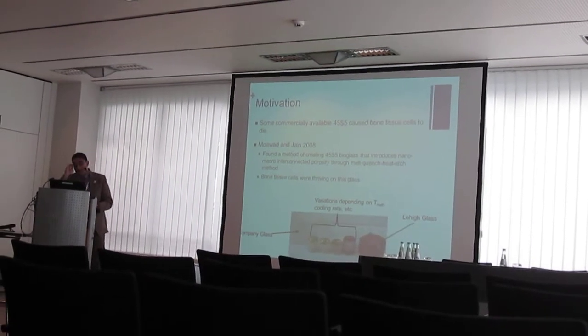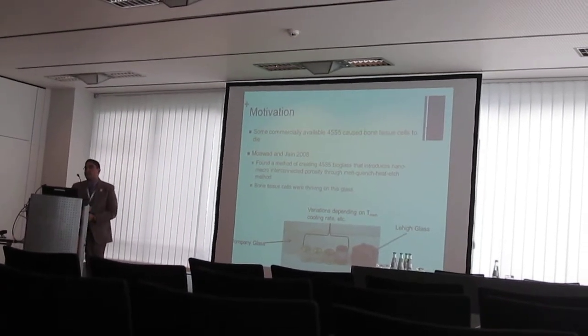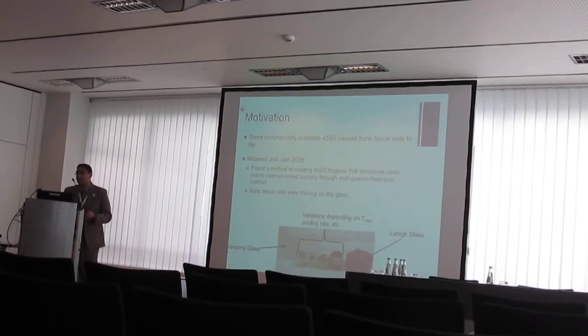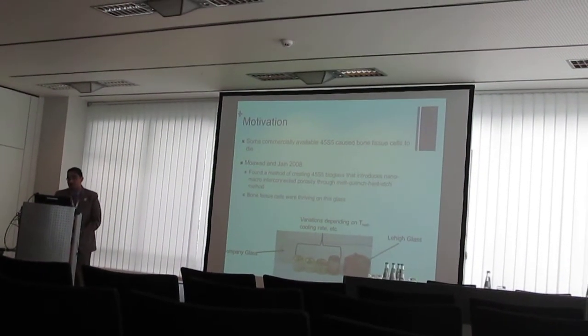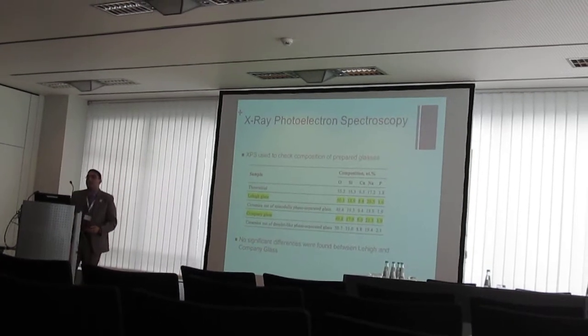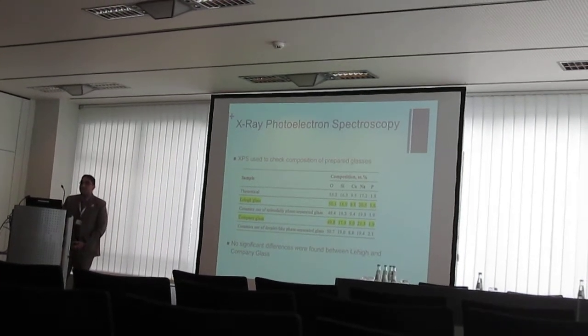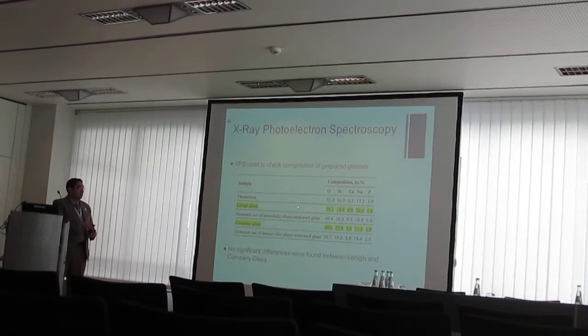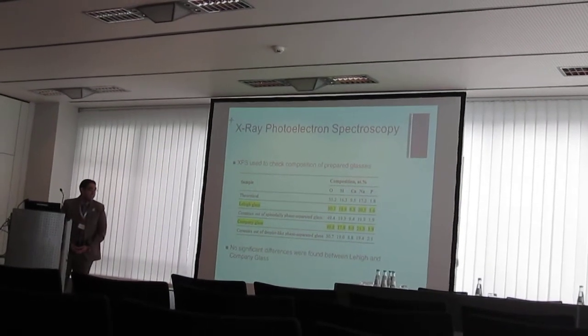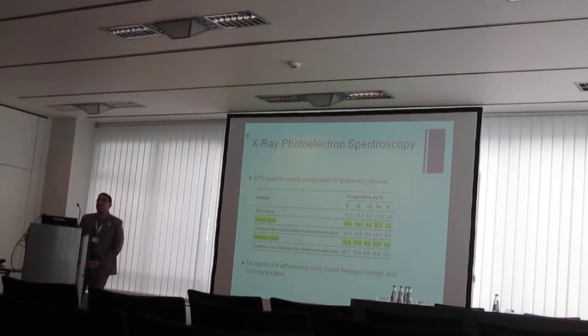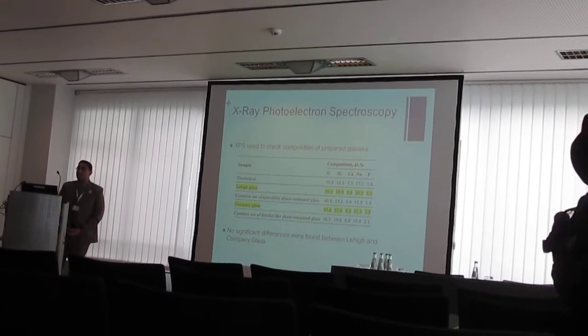We also wanted to find out if there was a different composition of the two glasses, to make sure we were comparing the same material. So we did some X-ray photoelectron spectroscopy, and the results are highlighted in yellow. You can see there were no significant differences found in the composition of the two glasses.